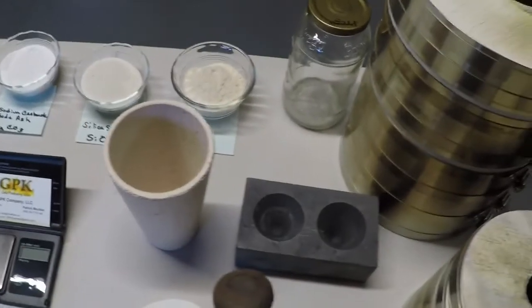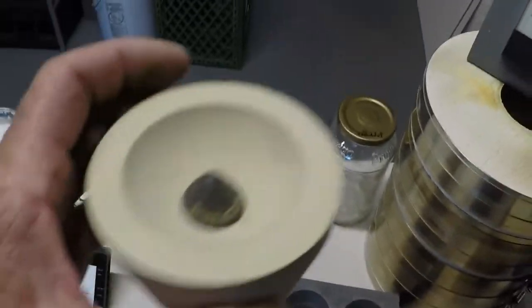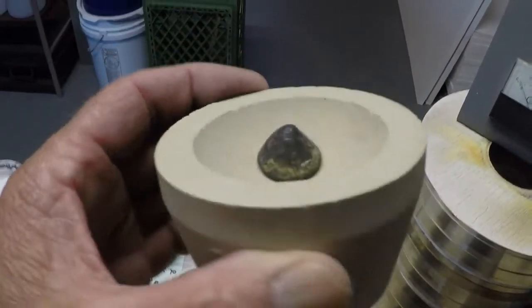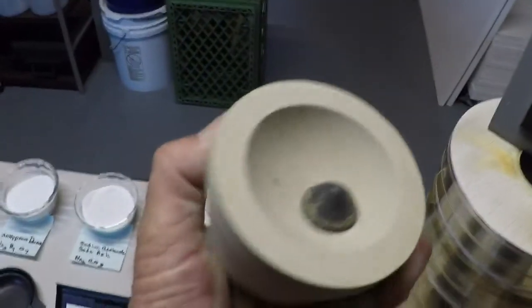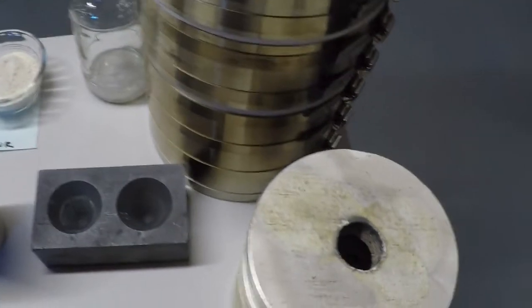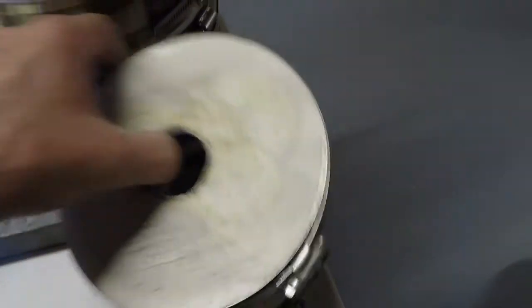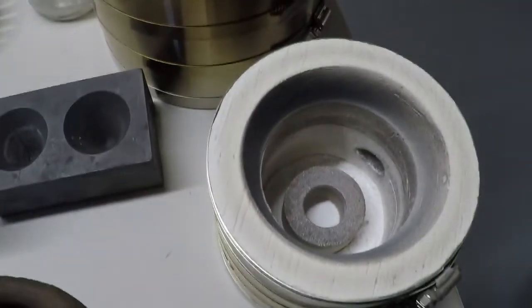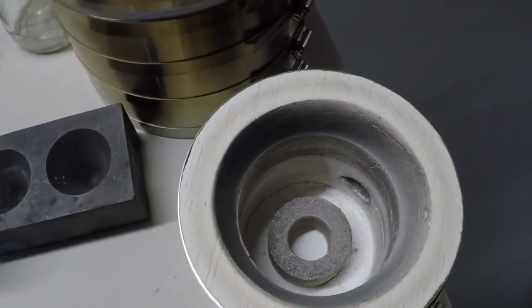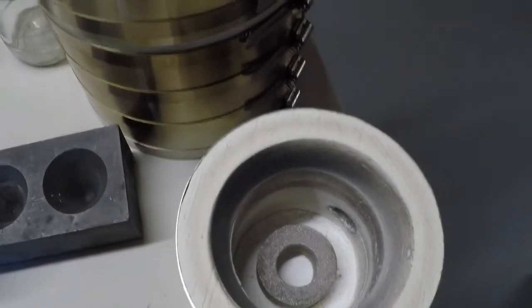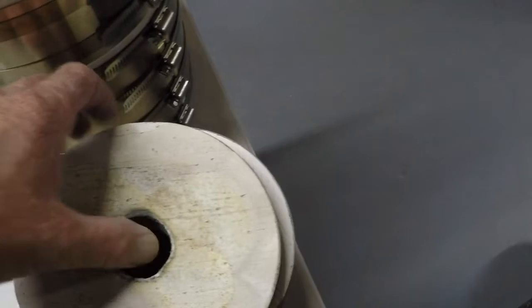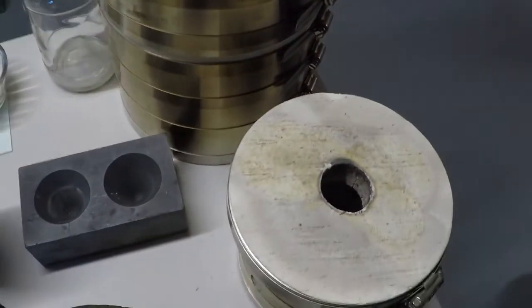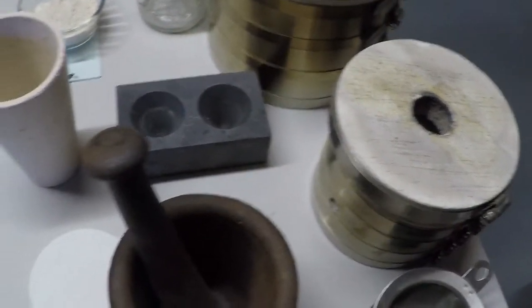And once we get it into a lead prill, we'll put it in a cupel. This is a large Mayber cupel that fits in the cupelling kiln over here, which is a modified KK6 with the ring and everything. We'll put our cupel in there, we'll cupel it off, and we should end up with a big bead of gold in the bottom of it all.